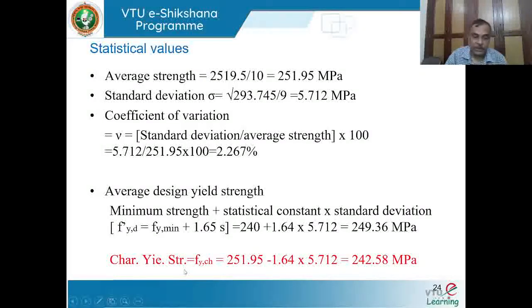But what is the characteristic strength that is to be used in the design? The characteristic yield strength is nothing but this mean value, 251.95, minus the statistical value of 1.64 into the standard deviation which you have calculated. So with this, 242.58 MPa comes into picture. So this is the value you need to use in design, and later this strength has to be reduced to take care of the uncertainties, where 242.58 needs to be divided by a factor. If it is the yielding case, 242.58 divided by 1.1 comes into picture, and that is the actual design strength to be used in the design.